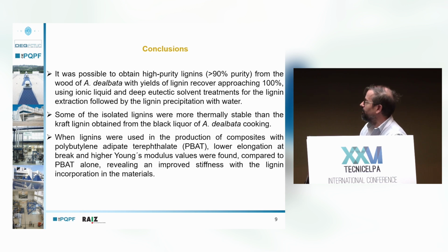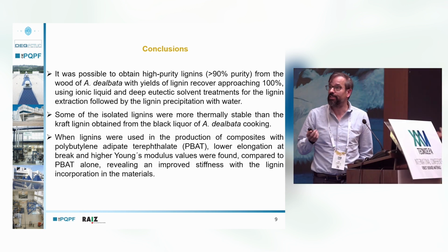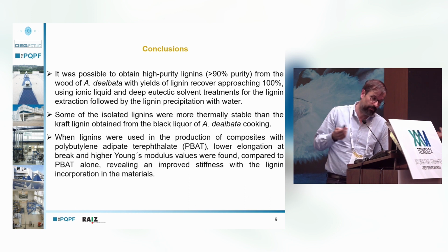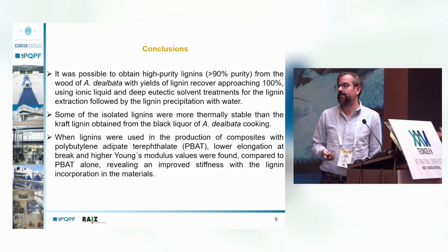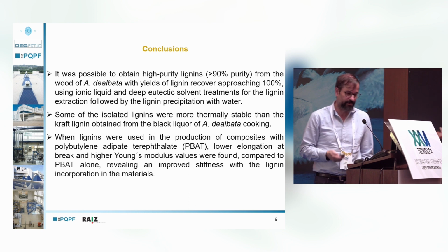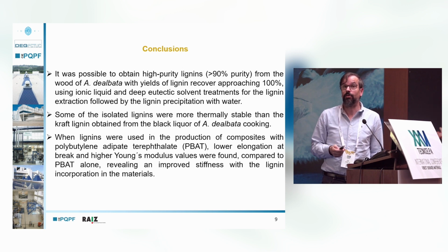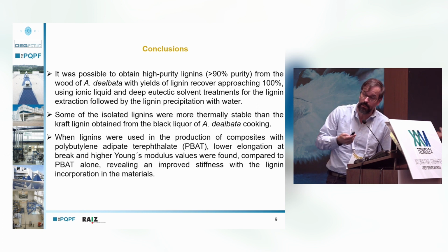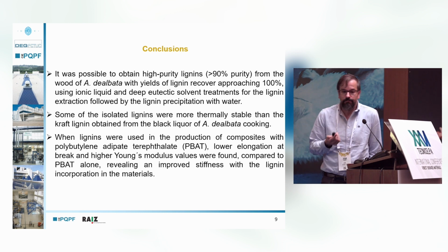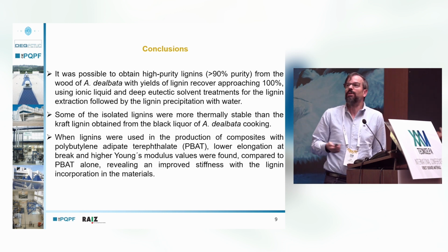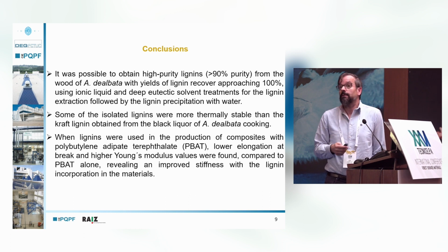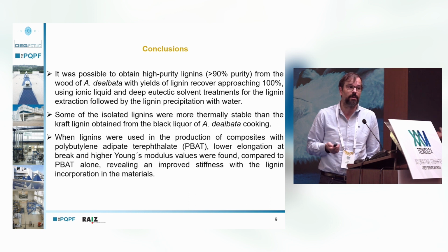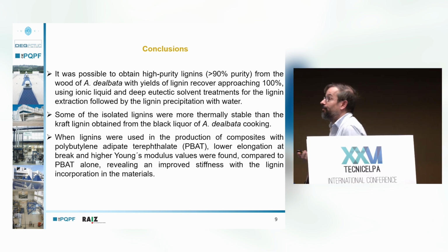When lignins were used in production of composites with PBAT, we have obtained lower elongation at break and higher Young's modulus values, compared to PBAT alone, which means that the stiffness was improved with the lignin incorporation in the materials. Finally, it's not here, but about the conclusions, we can say that for the particular case of PBAT, lignin seems to be a good approach to improve some of the mechanical properties and eventually to reduce costs, because we are talking about a byproduct of the pulp production that most of the amount is burned.